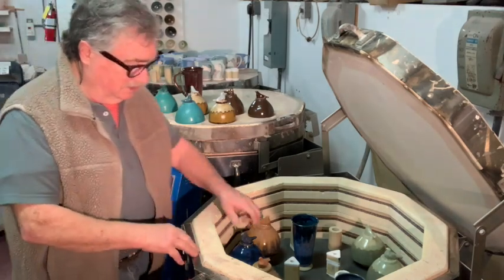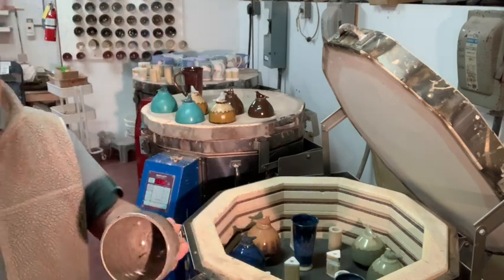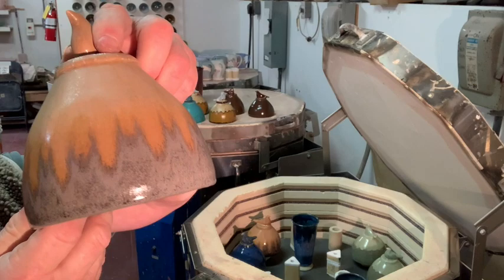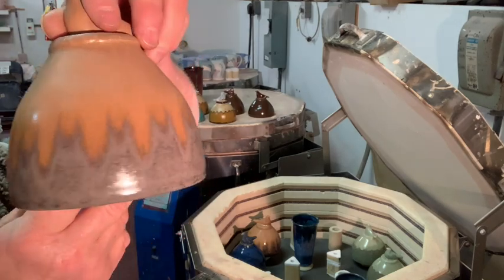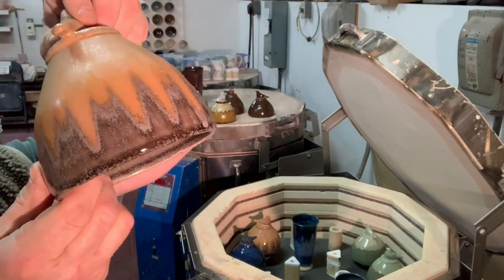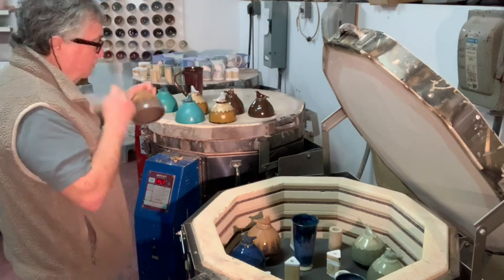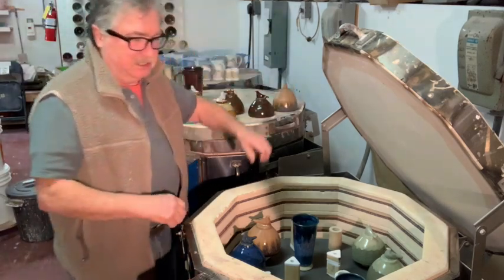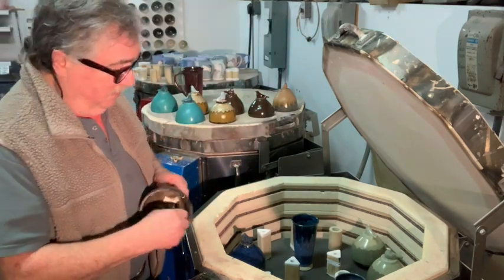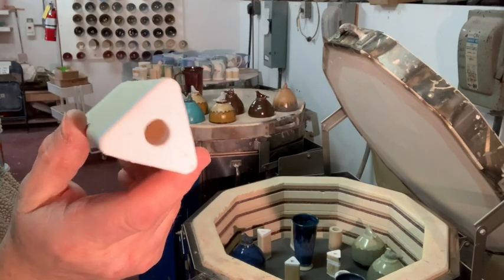We're only talking seven degrees difference. Even the grey — this is 125 degrees cooling. If you look at my other videos with the mouse grey, this is now totally opaque. It's crystallized as well, and the oatmeal ran into it the way I like the oatmeal to do, without running to the rim. I'm going to do a series of videos on oatmeal because a lot of people want to know how to do it — basically add tin or titanium dioxide; I add both to the same glaze.